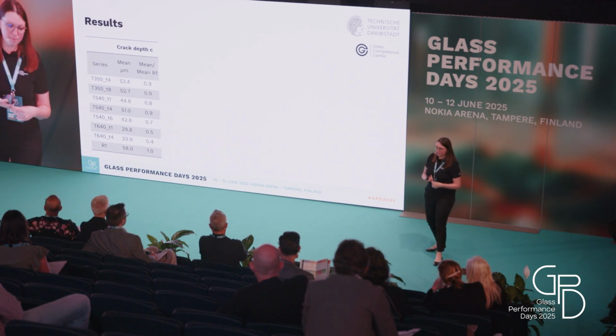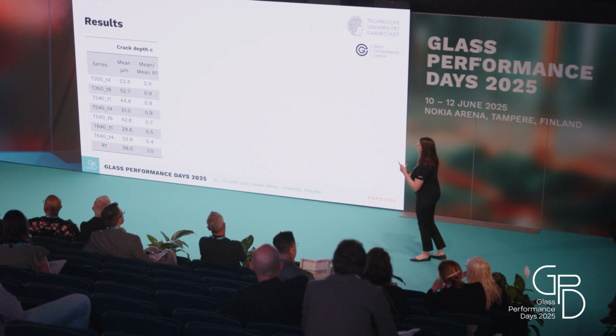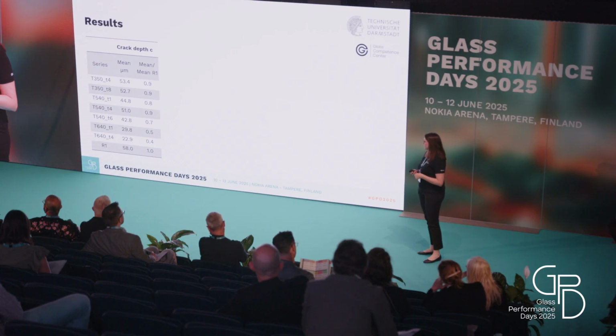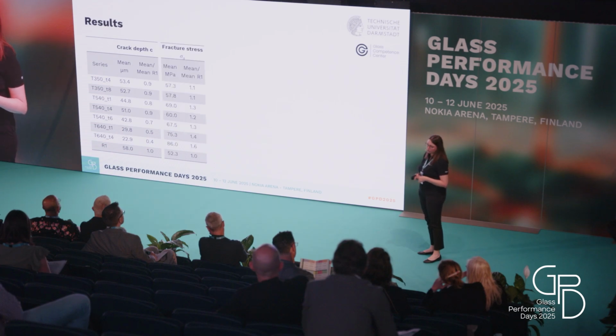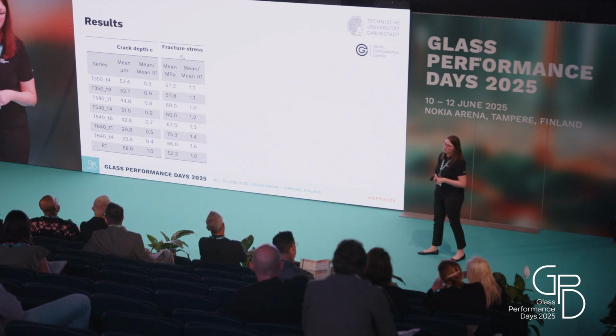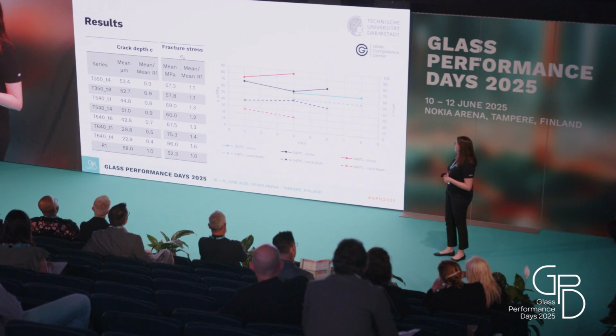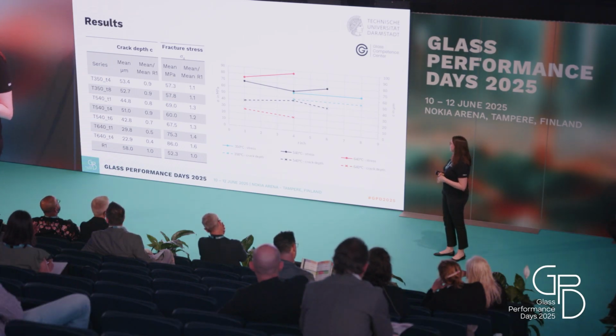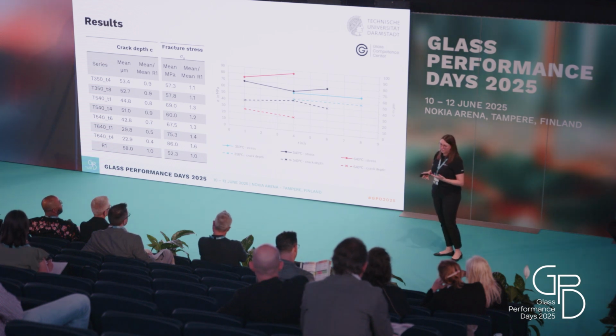For the crack depths, I have again a lot of numbers. Also here I will only present the mean crack depth divided by the mean from the reference series. And here we see that the crack depth has reduced for all the heat-treated samples. Comparing this with the mean fracture stress, we see that the increase of the fracture stress matches the decrease of the crack depth, which is good because it somehow proves the theory that I presented at the beginning.